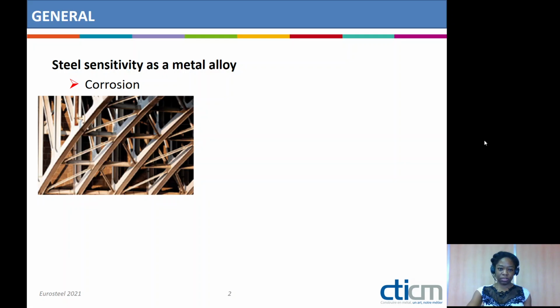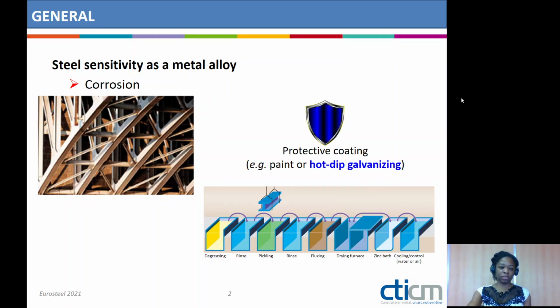Regarding steel as a metal alloy, it is sensitive to corrosion, which gives it a rusty aspect as you can see on the picture. Of course, solutions do exist in order to prevent or avoid this corrosion, like paint or hot dip galvanizing, which consists of different steps, including a zinc bath.